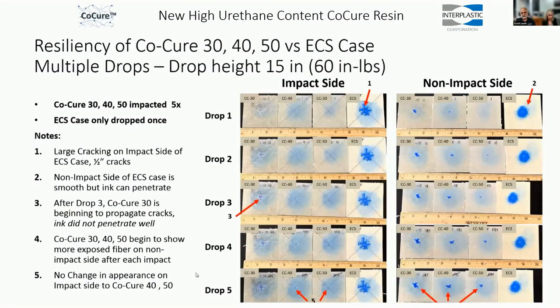And then you could get an idea of some of the property changes. Here we're looking at impact resistance, and this was a resin used for a container, not a Wabash project, another one. And you can see the regular resin, the impact zones here. And then as we increase the co-cure level, you can see the effect on impact.